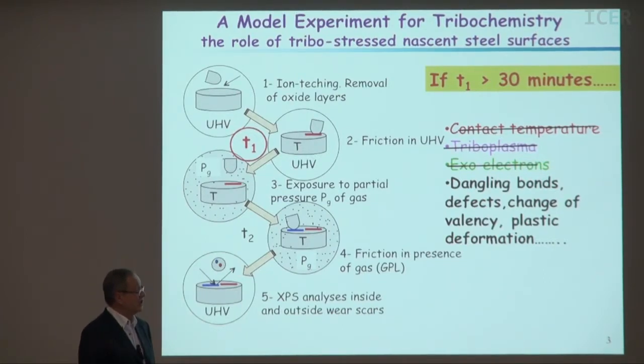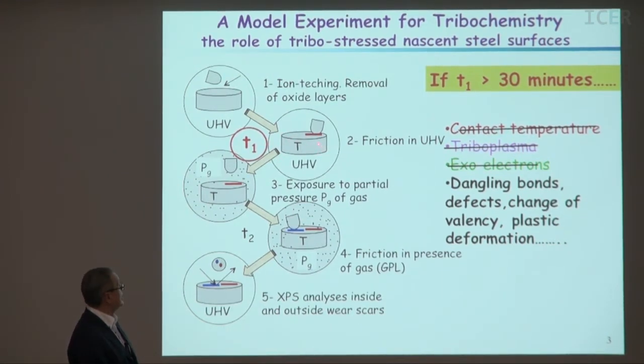Our strategy was to use a vacuum chamber, putting the sample in a high vacuum chamber. In this vacuum chamber, we can, if we want, remove the oxide layer, for example on steel, and have a friction of iron on iron. After that, we can make a friction under UHV condition. After that, we can introduce the gas and make the friction in presence of the gas. Finally, we pump out the gas, and the sample can be transferred to an analytical chamber for surface analysis. So we can identify the chemical reactions occurring by XPS or Auger.